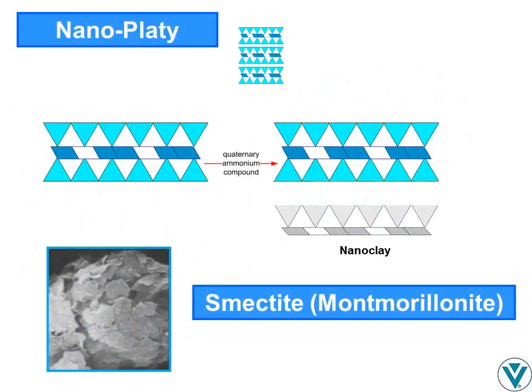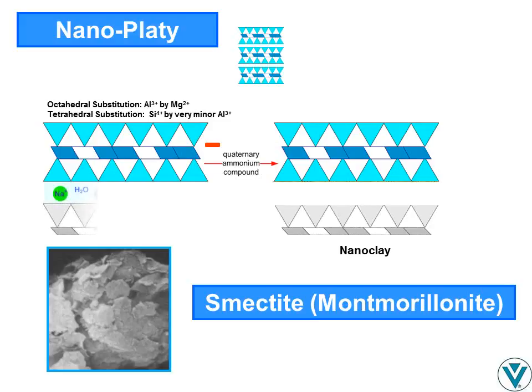Smectite clays are differentiated from similar phyllosilicates by their ability to hydrate — that is, absorb water between plates — to a much greater degree. Montmorillonite, the most common smectite, has limited substitution of octahedral Al3+ with Mg2+, and very minor substitution of tetrahedral Si4+ by Al3+. This gives the lattice a net negative charge. Because the charge arises primarily from the octahedral layer, it is relatively weak. This is balanced by exchangeable cations, either mostly sodium or calcium, between the clay plates. Tightly held oriented water also occupies the space between individual plates. In the dry state, monovalent exchange cations are typically accompanied by a single water layer, divalent cations by two layers. The weaker octahedral layer-derived charge allows montmorillonite to incorporate more interplate water than can minerals of similar structure.